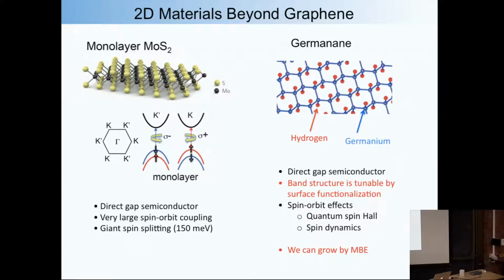And the fact that you have this kind of depletion, for one thing, it's possibly problematic for spin injection or spin Hall effects, which we're trying to do in here. And the other thing is, if you're trying to do 4-probe contacts, you just can't place them on top like you can do sometimes in graphene. We haven't done this yet, but we realized that if we want to do 4-point probe measurements, we have to etch it down and have the contacts far, far out of the channel. Otherwise, they'll just remove the carriers and make 4-point probe make no sense, right? So I think that the transport measurements are very tricky, and getting ohmic contacts and so forth is also very tricky, and we're working on that aspect right now.